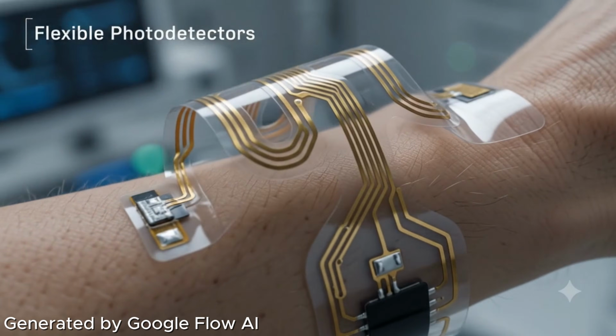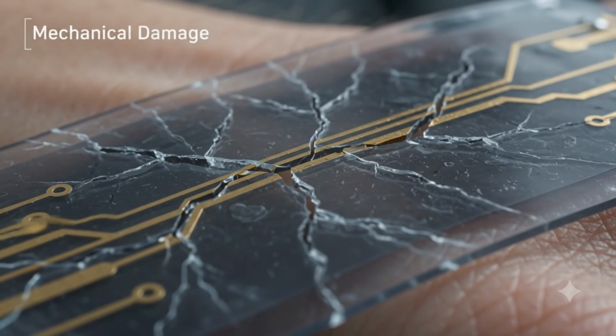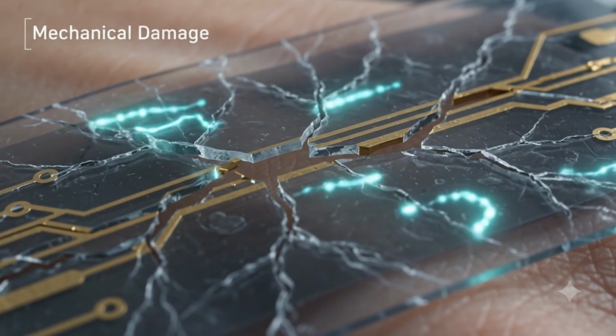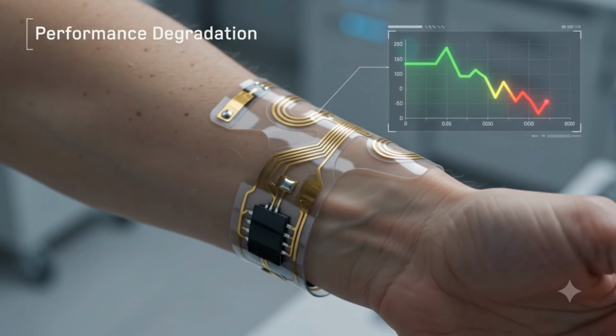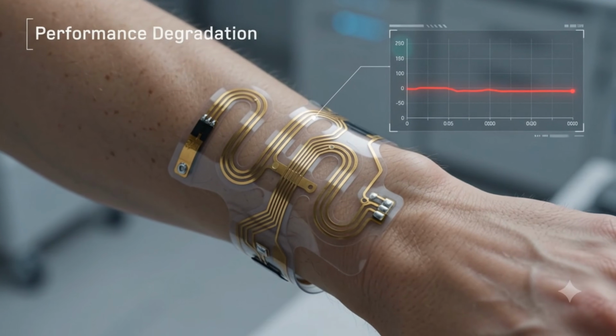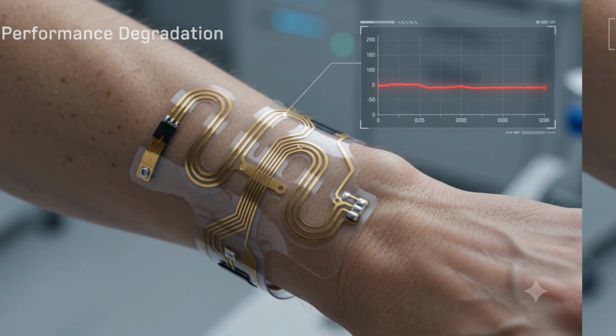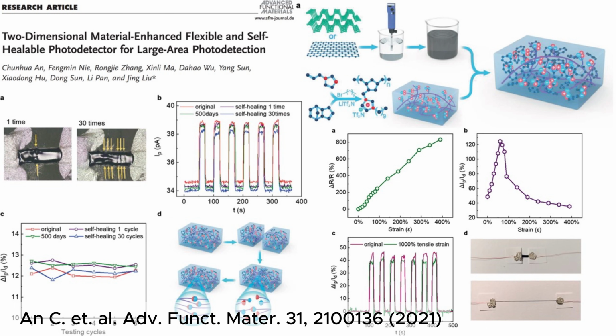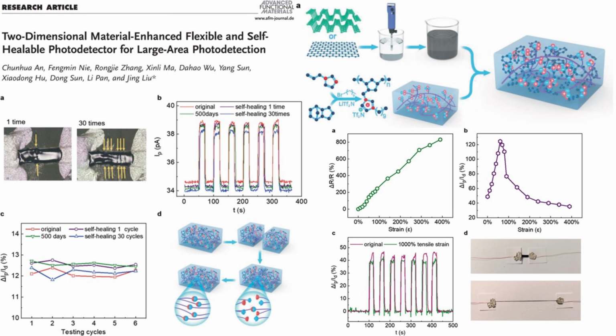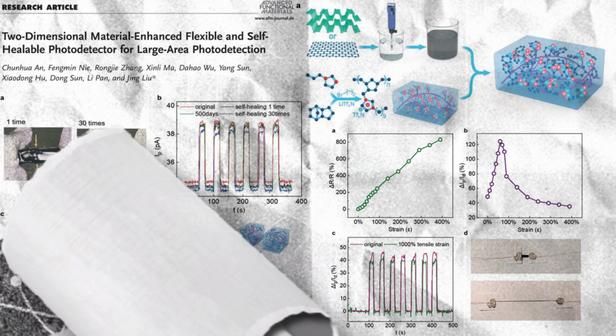Another promising application is flexible electronics. Flexible photodetectors are widely used in wearable devices and electronic skin. However, repeated deformation can create cracks that decrease performance and eventually lead to device failure. To address this challenge, researchers incorporated graphene and black phosphorus nanosheets into a self-healing ionic polymer. The nanosheets enhance light absorption, while the polymer matrix provides flexibility and self-healing capacity. The resulting photodetector recovers its photoresponse after 30 healing cycles, remains stable after 500 days of storage, and continues operating under strains of up to 100%.